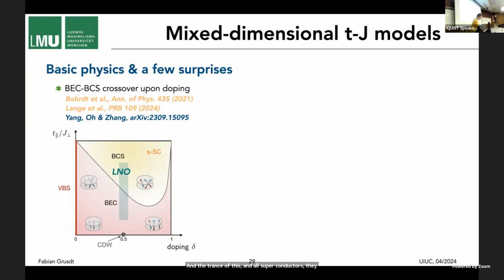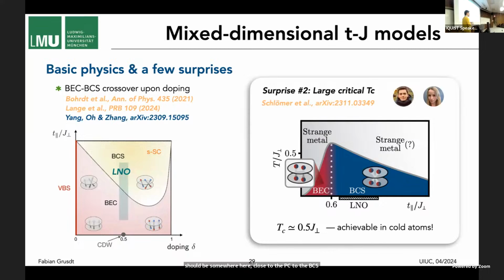And we looked at this in more detail now, motivated, of course, by the discovery of these LNOs, and found that yes, indeed, these LNOs, if we estimate parameters, should be somewhere on the BCS side, close to the BEC to BCS crossover.